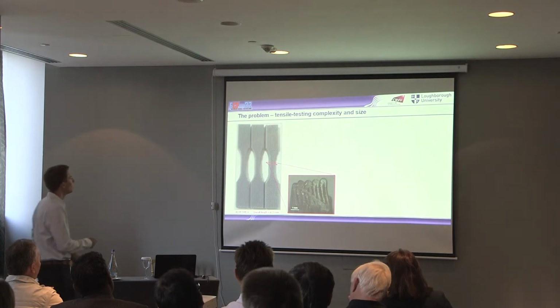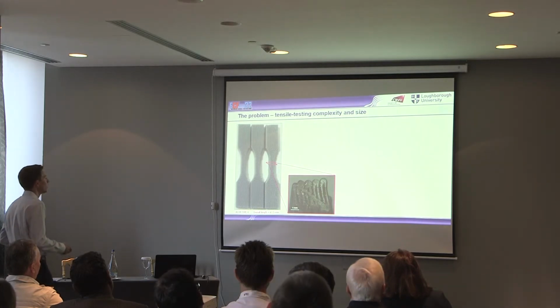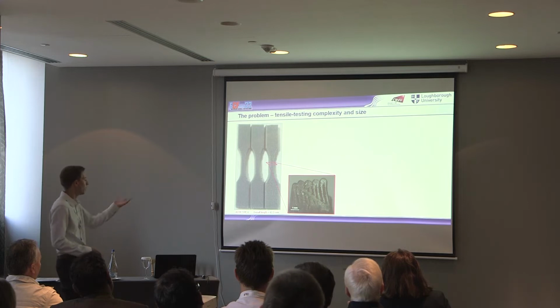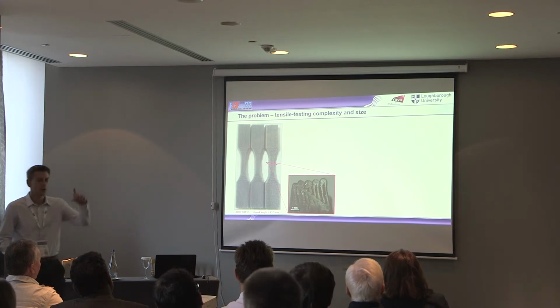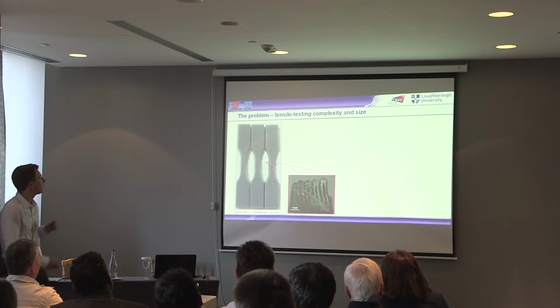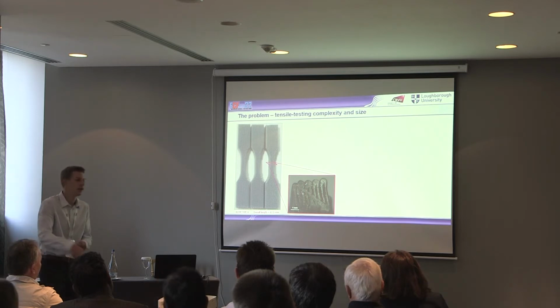So this is looking in a little more detail at the current way that you generally test. We've got these ASTM type dogbone samples, about this big, and in that narrow gauge section, this is what it looks like after fracture. You can see, as I was describing before, there are filaments that have been laid down.